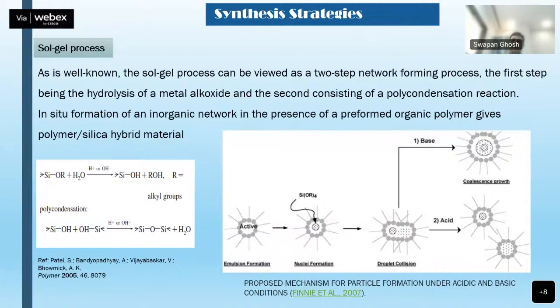But the beauty here is that, let's say here we're talking about a silicon oxide core polymer shell. We can also design the opposite way, a polymer core silicon oxide shell. We can also think about the polymer core silicon oxide shell, but later on the polymer is dissolved, and you can think about a hollow particle. This hollow particle can find different applications, for example, sound absorbing. We can also load that later with some sort of pharmaceutical ingredient and so on, which can be used for biomedical applications. So in one word, the sol-gel method is widely used to encapsulate different types of ingredients in a silica matrix, or the silica matrix contains the ingredient and further polymer is coated onto that.